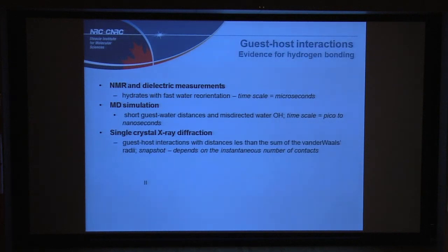And then single crystal X-ray diffraction. Here, of course, we can actually determine the relative positions of the atoms, both of the guest and the host, and look for guest-host interactions with distances less than the sum of the van der Waals radii. And if you find these, this means that there is a special interaction that a short-range model just would not have.